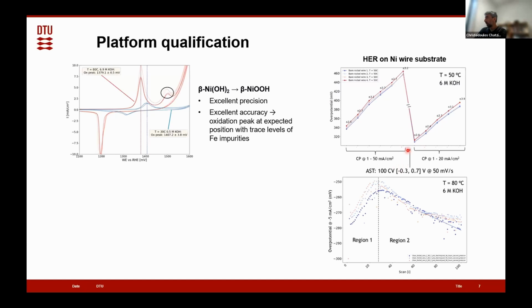Then the protocol we used included an accelerated stress test protocol, including 100 CV cycles, going from negative cathodic potentials up to 0.7 volt. And again, we saw a quite complex profile of the overpotential at cathodic conditions of -5 milliamp per square centimeter after each one of these 100 cycles. At the beginning, we see an activation of the HER response, followed by a deactivation. We have a working hypothesis of what is the physical processes behind this profile here. But what is important to stress here is actually the reproducibility of this complex behavior in different measurements. And then again, doing hydrogen evolution reaction measurements after the AST protocol, again, we see very reproducible performance.